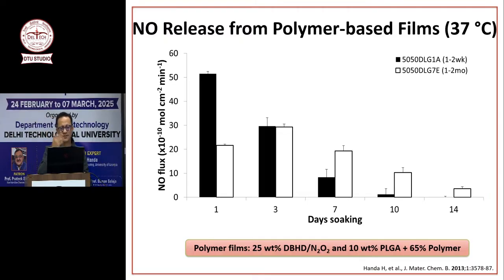One question. In the black one, since it's degrading acid very fast, since the polymer is not a metal, would it cause acidic corrosion or something? Not acidic corrosion, but it can be toxic. Like the levels of nitric oxide release are very high, more than 10 times what that computational modeling number showed. See, the thing is how science moves. I published this paper 10, 12 years ago when I was working with my PhD mentor, Dr. Bartlett. We were not doing toxicity studies at that time. We didn't have the facility to do toxicity studies, so we never tested this material for toxicity. But it could have been toxic.